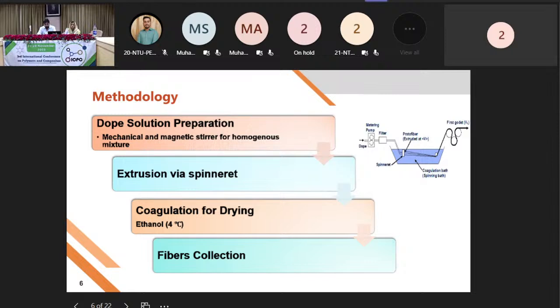Magnetic stirrer mixing for homogeneous solution preparation. Later on, the material is extruded through the spinneret, and then it is coagulated in the coagulation bath made of ethanol. The fibers obtained were collected after rinsing processes. The picture on the right side explains the complete process.